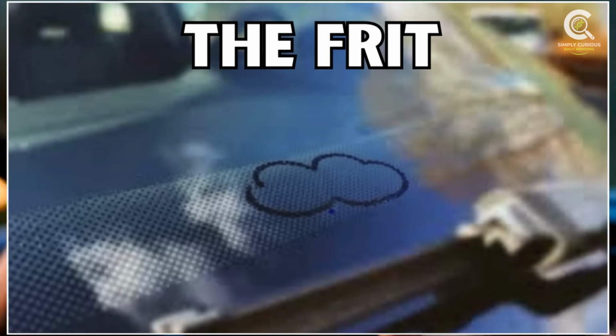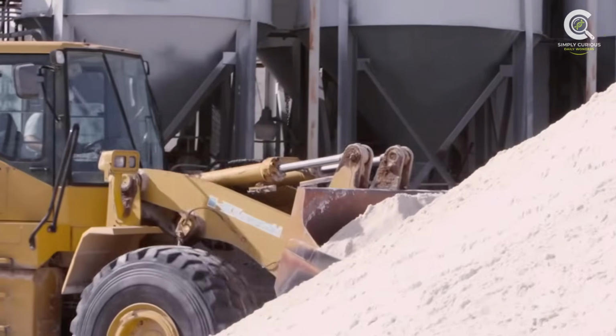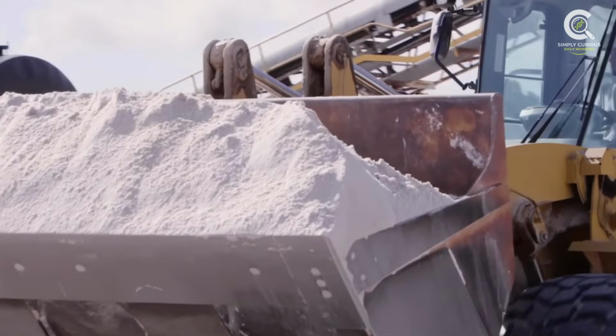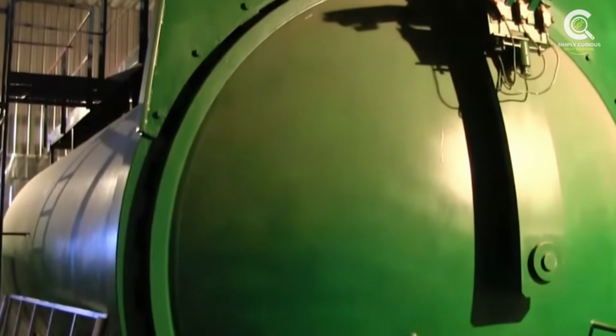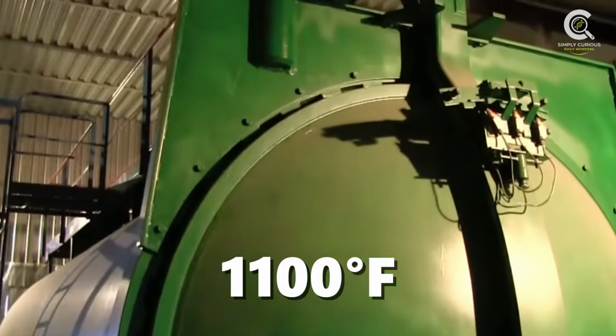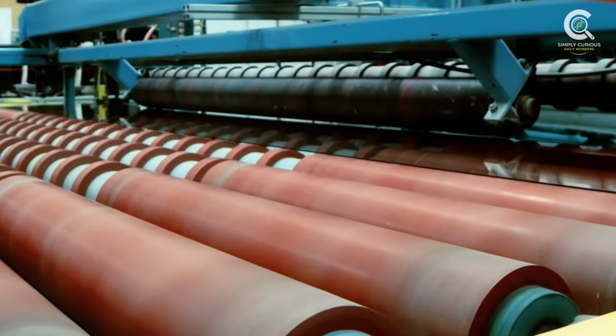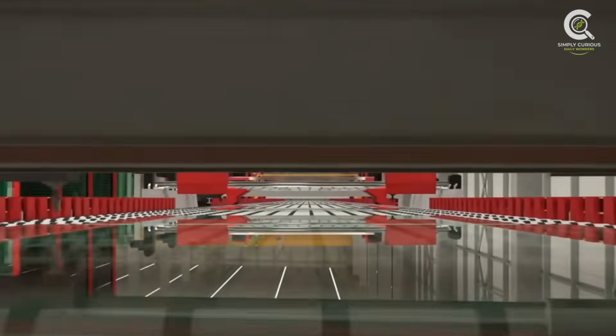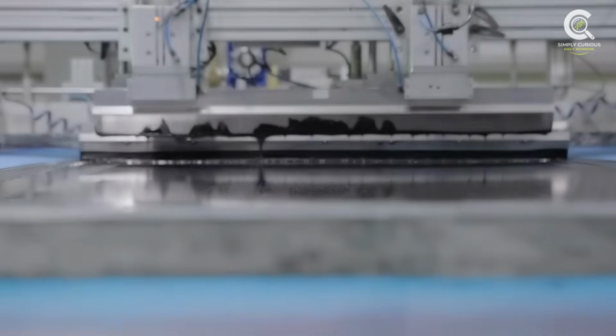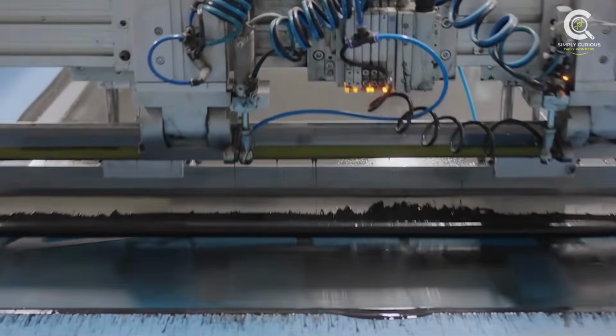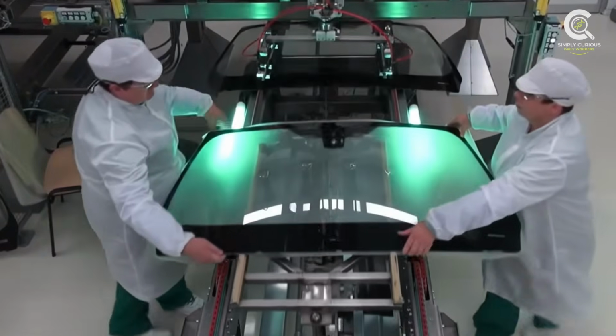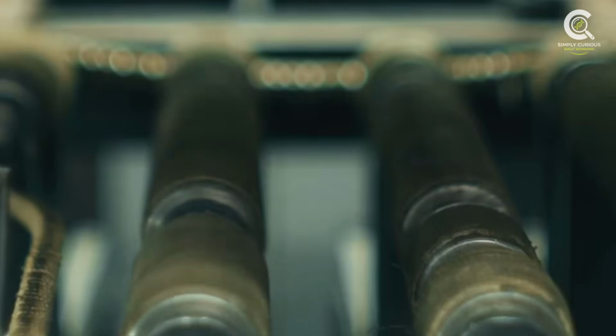The frit is not a coating on the glass. It cannot be scratched off because there is no surface to scratch it from. The frit starts as a ceramic enamel, powdered glass fused with metallic oxide pigments, applied to the raw glass sheet through a silkscreen process before the windshield goes anywhere near its final form. Then the entire assembly goes into a furnace, reaching temperatures above 1,100 degrees Fahrenheit. At that heat, the ceramic doesn't just bond to the glass, it melts into it. When the windshield comes out of the oven, there is no longer a layer of frit sitting on top of a layer of glass. There is just glass, with a black region and a clear region and no seam between them.